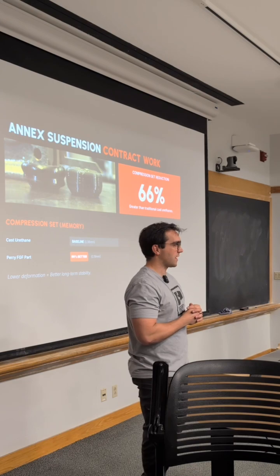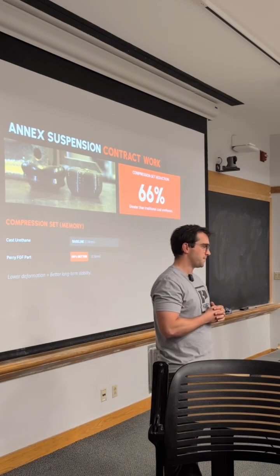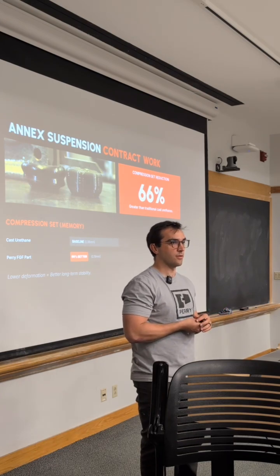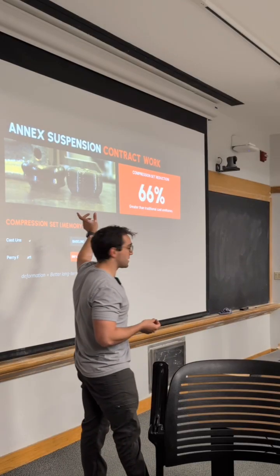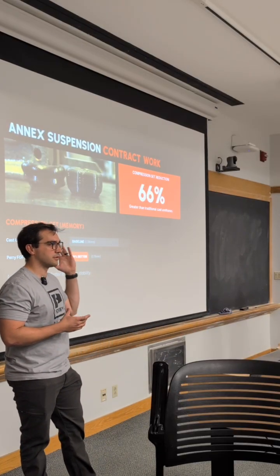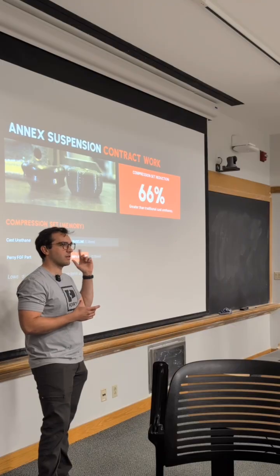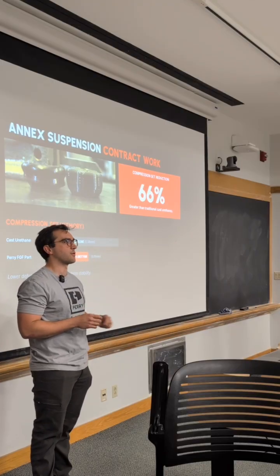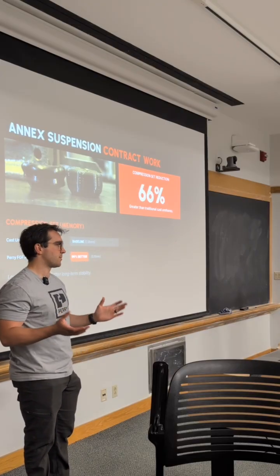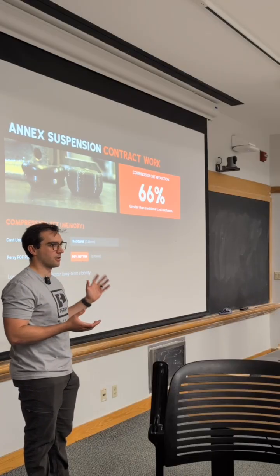Their part was failing in the field reliably due to compression set. And so the parts you can see here on the left, that's after being loaded up with, I think we tested at 3,000 pounds sustained for 24 hours at 25 C. So ambient temperature, like a little over a ton.